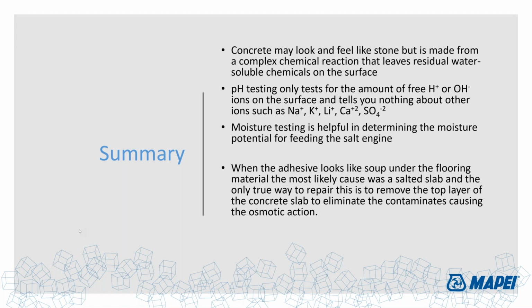So if you've got a lower water to cement ratio, below 0.45 or 0.4, first of all, it's going to be a bitch to place. It's going to be very stiff, but the porosity is going to be considerably less, and your moisture vapor emission rates will decrease by that. I've seen concrete slabs that have moisture vapor emission rates less than 3 pounds, 2.5, even 1.7 pounds, but the RH levels are 99%.